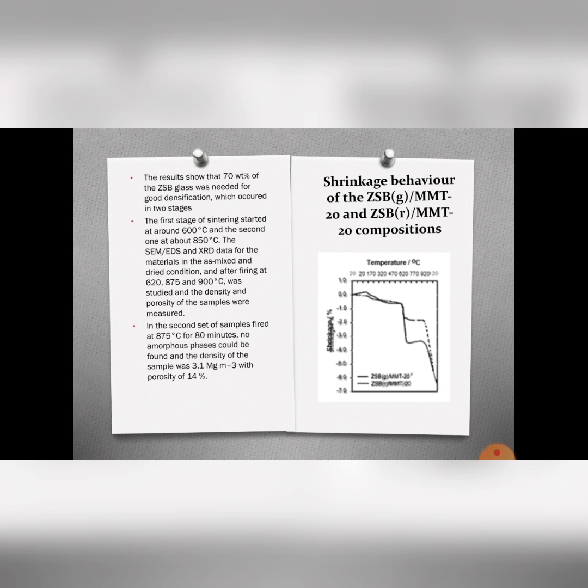In the second set of samples fired at 875 degrees Celsius for 80 minutes, no amorphous phases could be found, and the density of the sample was 3.1 Mg m^-3 with porosity of 14%.